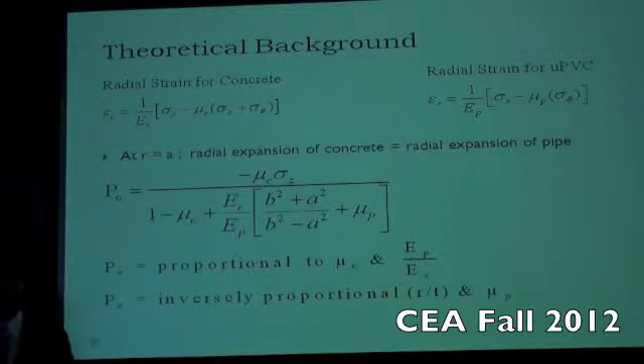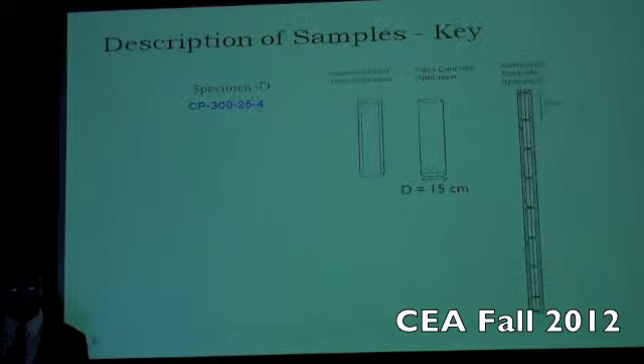Okay? From this, we can note that the confining pressure exerted by the pipe on the concrete, which from our theory we need to give the concrete core its strength, is proportional to the concrete's Poisson's ratio and the ratio of the modulus of elasticity of the plastic divided by the modulus of elasticity of the concrete. And it's also inversely proportional to the ratio of the radius to the wall thickness and the Poisson's ratio of the plastic.